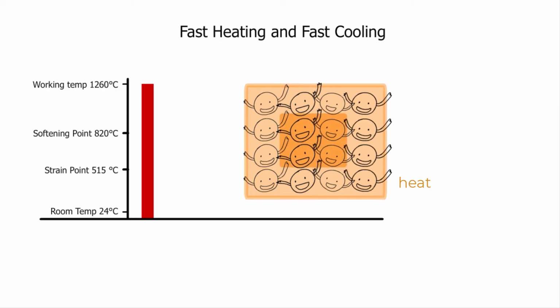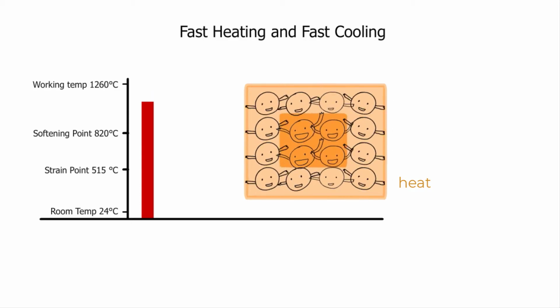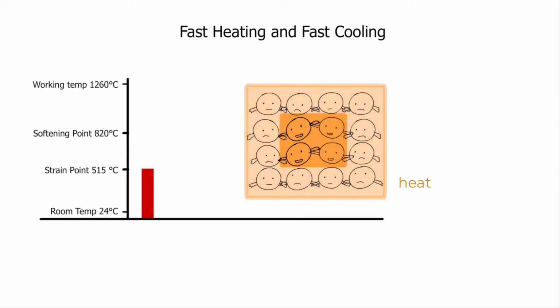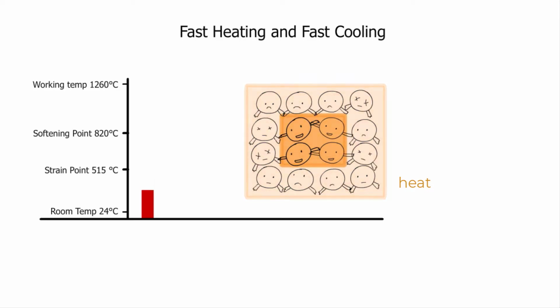When we finish heating the glass, the temperature on the surface will drop much faster than the core. When the outside temperature becomes 515 degrees Celsius again, the surface gets stiffened while the core is still soft. And again, the temperature gap causes internal stress. When the stress becomes too great, the bondings break and the glass will crack.